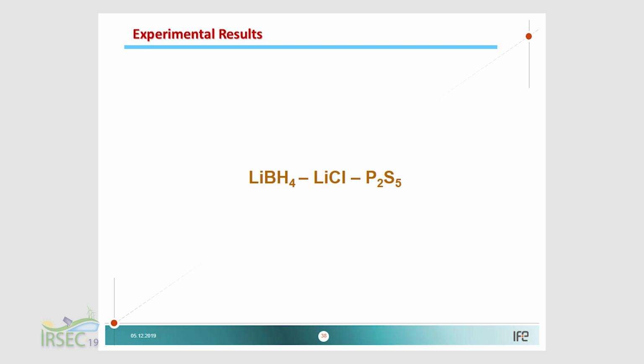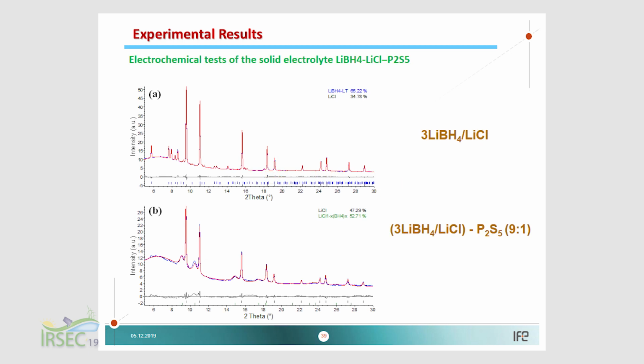The last point is that, instead of iodide, we also used chloride, so we tried to study this system. Quickly, I will just give a short summary. We know that with the chloride, in fact, we don't form this hexagonal phase, because the phase reverses back